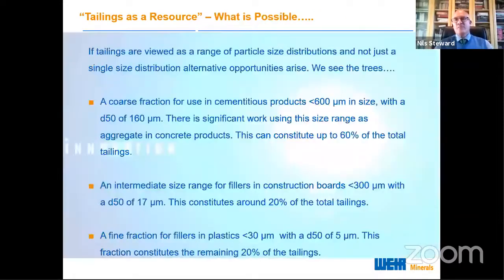So, what is possible? You've seen a lot of things are possible. And if we view tailings as a range of particle size distributions and not just a single particle size distribution, we start to be able to see the trees. If we separate out a coarse fraction, the less than 600 microns, and we actually use that in cementitious components, we can actually pull out 60% of the material and make essentially cementitious components out of it. But again, market, location, we've got to see what can be done.